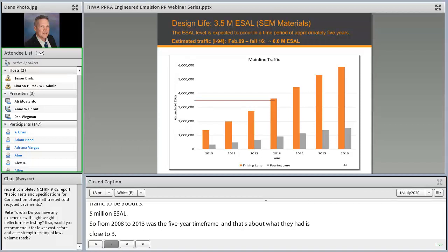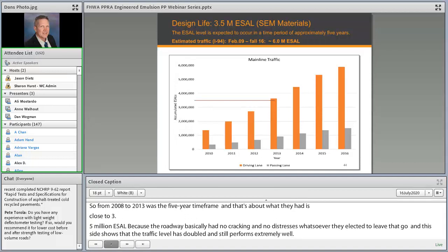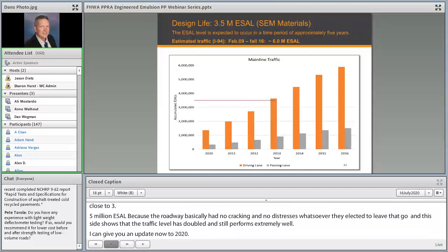And I can give you an update now to 2020: the cells are still in place after 12 years of traffic loading, and there's still very little distress on those cells. They were recently cored because some people had concern about whether or not the engineered emulsion would maintain the underlying base material in a bound state. And I can tell you that the pictures of the cores and how those cores came out were extremely good. They all looked very good.